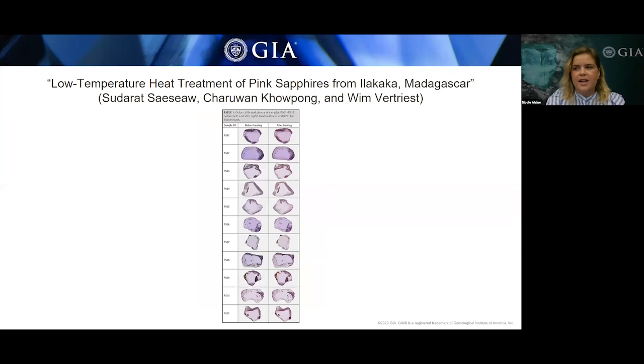So pictured here are 11 samples reportedly from Ilakaka, Madagascar, and show before and after heat treatment. They ranged in sizes from 0.41 carats to 2.15 carats and are all polished with at least 2 windows for data collection. 9 of the 11 samples were purchased directly from the miner, but not at the mine. And if you are familiar with GIA's colored stone reference collection, this classifies them as C-type samples. 1 was acquired from a trader in the market and is classified as an E-type sample. And 1 was purchased from miners at a washing site, which defines it as a B-type sample.